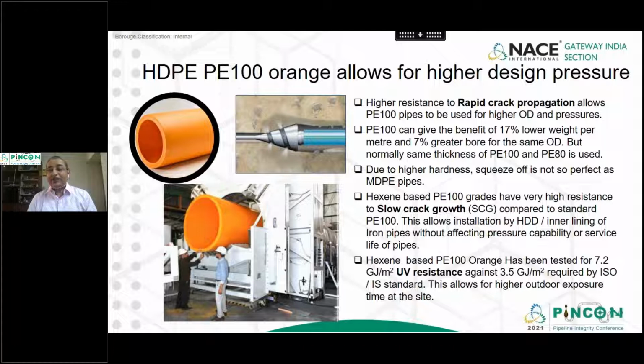This is because normally gas pipes do not fail due to internal pressure. They mainly fail due to third-party disturbances because different pipes can be in the same trench. So if it is a thicker polyethylene pipe, it can resist the hit from a crowbar much better than a thinner pipe. And also the thickness of the pipe addresses the kinking issues. In HDPE PE100, due to higher hardness, squeeze-off is not as perfect as with MDPE pipes.